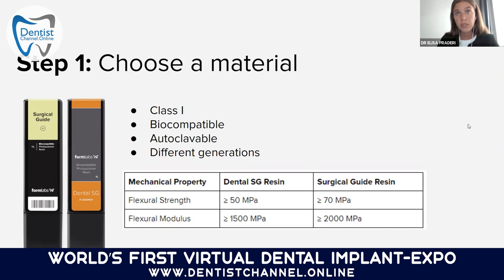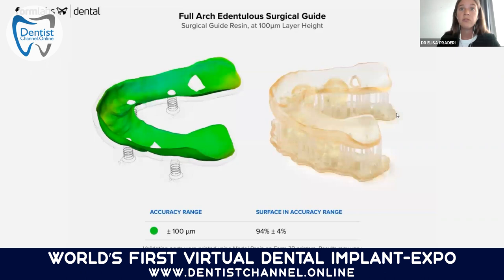After we choose the material, we also need to see that the accuracy for that application is good, according to the layer height in which we print. For example, when doing this accuracy study for a full arch dental surgical guide printed at 100 microns layer height, we see that we have a surface accuracy range of 94%, which is very good and sufficient for this application.